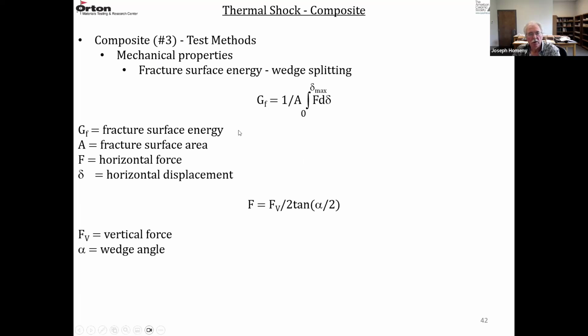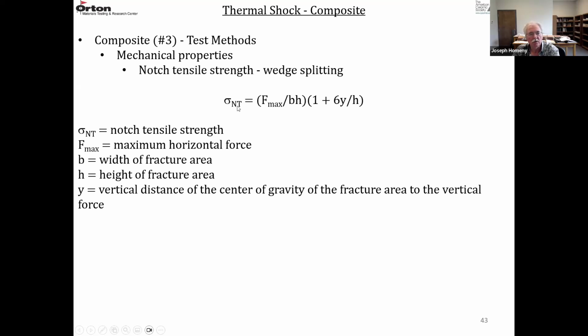And I'm just reviewing these equations again. This is the wedge splitting fracture surface energy, GF, 1 over A, and the integral of F d delta. And F here, emphasize that it is the horizontal force. So FV is the vertical force when you apply the force of that wedge. So F is calculated from FV, the vertical force, divided by 2 tangent of alpha over 2. Alpha is the wedge angle. So you measure the vertical force in the mechanical test machine, and then you calculate the horizontal force with this equation. And again, this is the notch tensile strength.